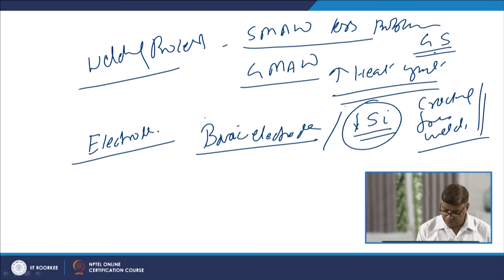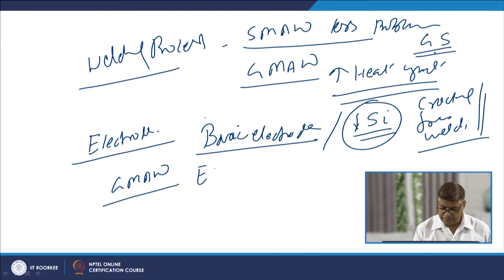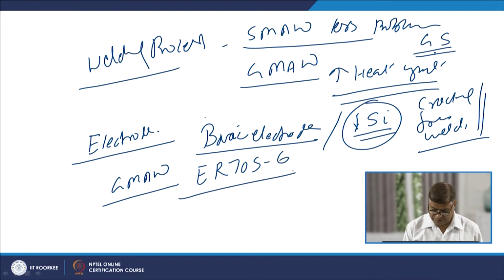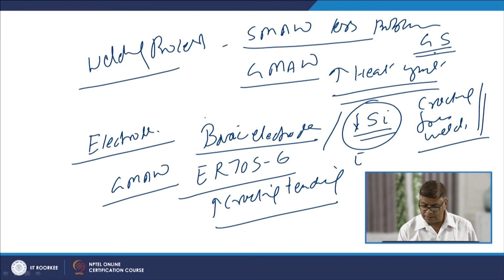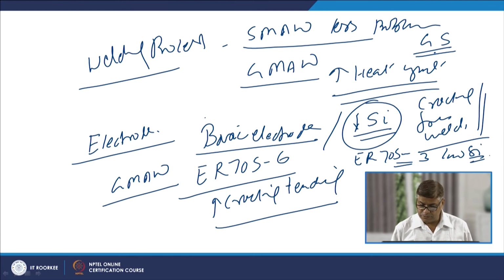For example, in case of the GMAW process, if we use a typical filler like ER70S6 type, which has a higher concentration of silicon, it increases the cracking tendency significantly as compared to the case when ER70S3 type low silicon electrode is used. This reduces the cracking tendency significantly. So, use of suitable welding consumables having lower silicon will facilitate developing weld joints which are free from cracks.